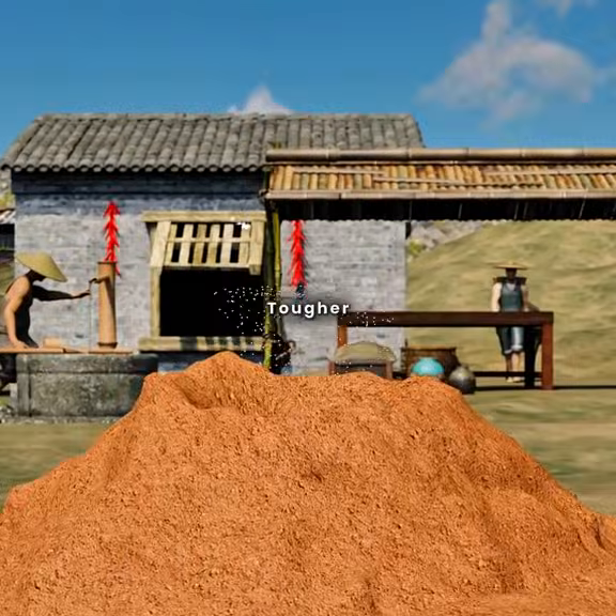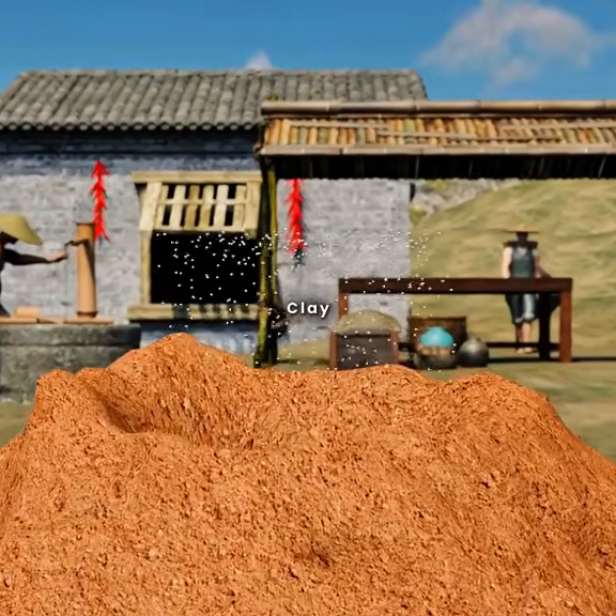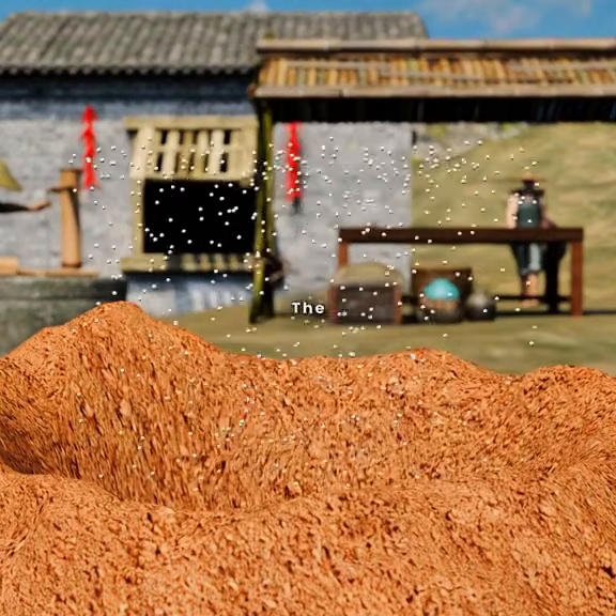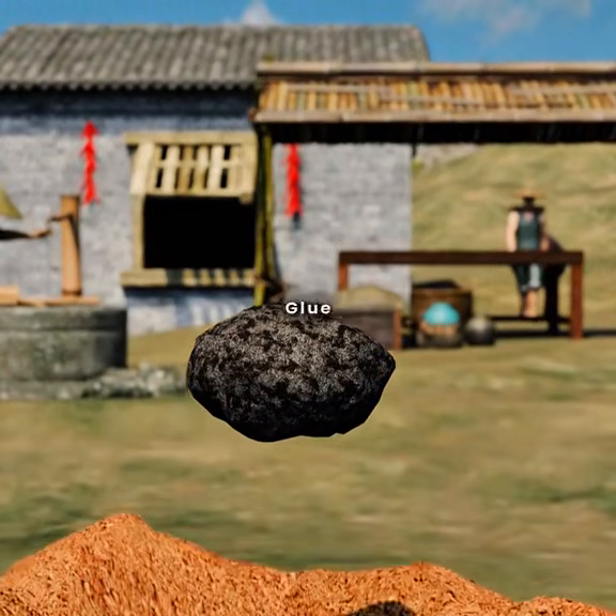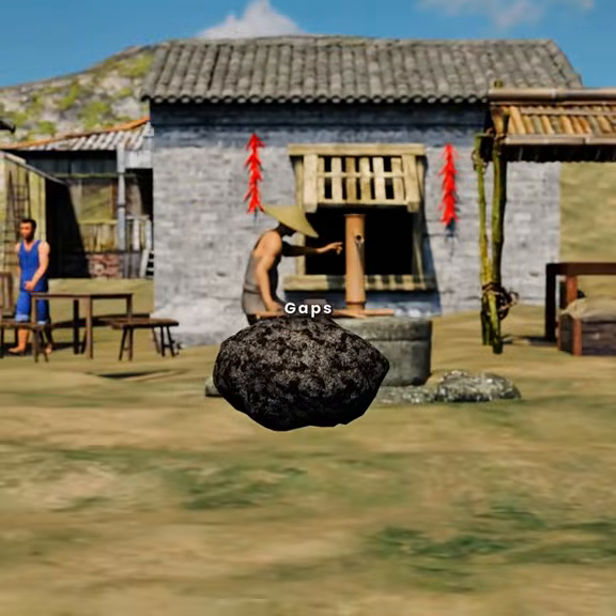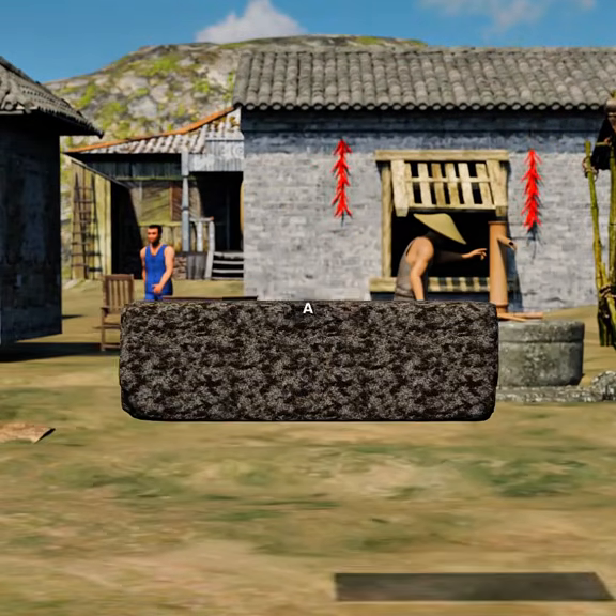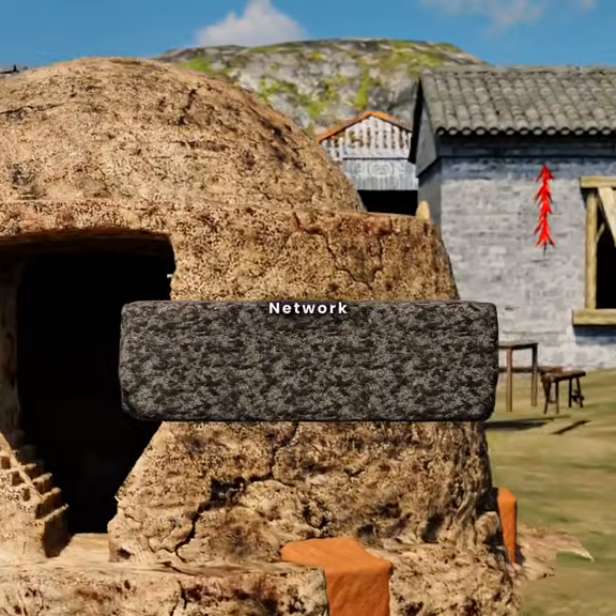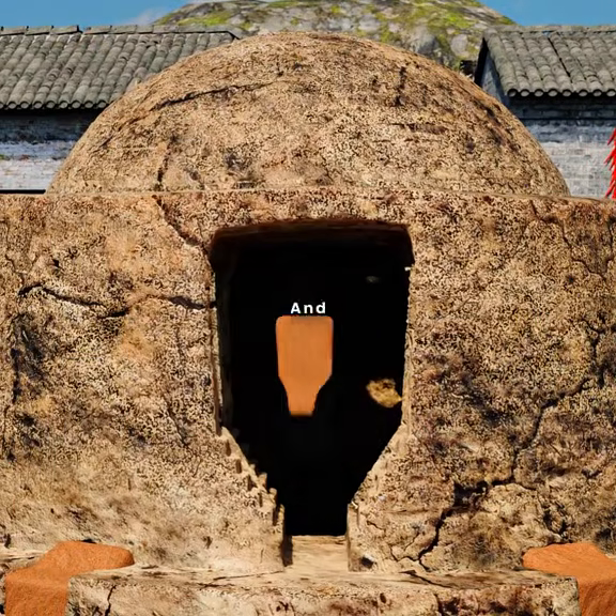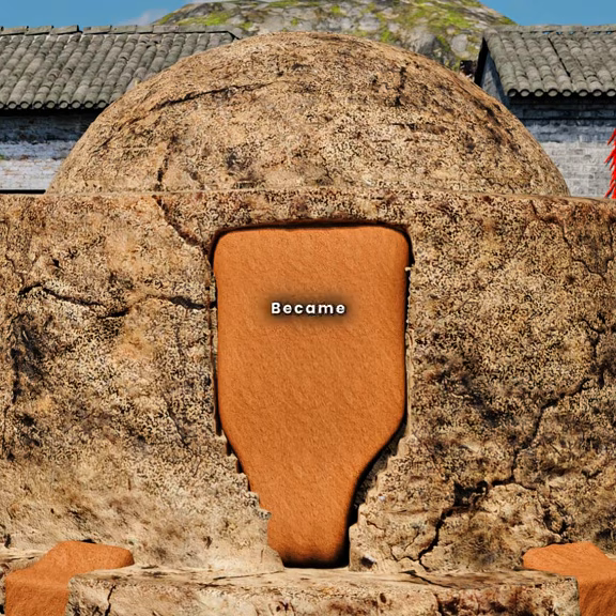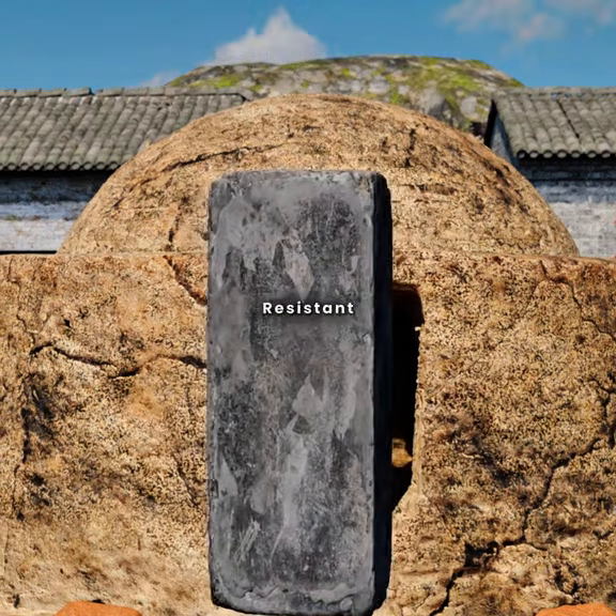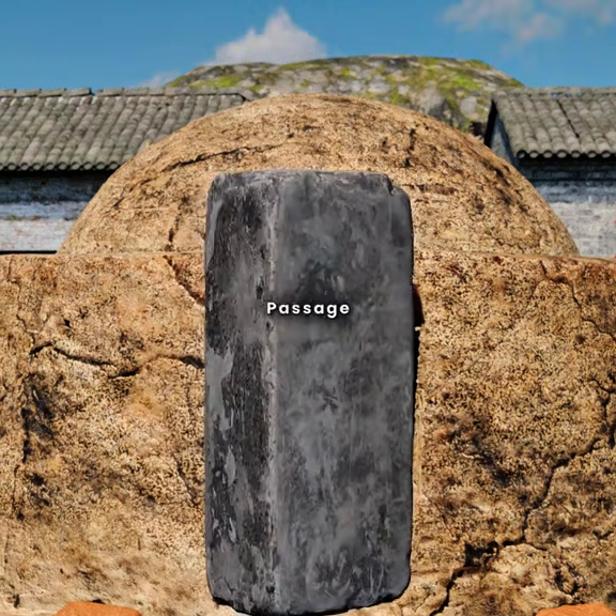For even tougher bricks, while preparing the clay, they mixed in glutinous rice powder. The starch from the rice acted as a natural glue, filling microscopic gaps between clay particles and forming a flexible, web-like network. After undergoing the same kiln firing and water pouring process, these bricks became remarkably dense and highly resistant to wind, rain, and the passage of time.